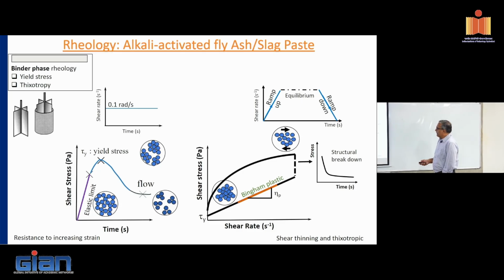What do I expect to get when I do the ramp up? Because this has a yield stress, it will start flowing only after I overcome this, a shear thinning liquid. This is during the equilibrium part where I'm holding the strain rate constant. What happens here? The structure breaks down. So the stress resistance starts decreasing, right? And then when I ramp down, I come down here, and usually the ramp down is a Bingham plastic. This is what we get for cement paste.